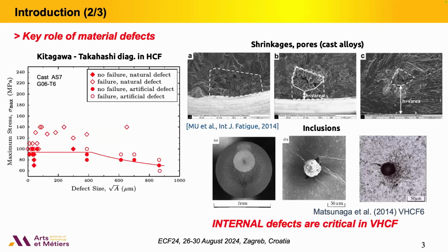But the problem is that such a diagram doesn't explain why, when you decrease the stress level, the fatigue crack initiation shifts from the surface to the interior. Up to now, we know that the critical defects are in the material, and they give a typical pattern like the fish eyes here, but we do not explain why there is this shift from the surface to the core.